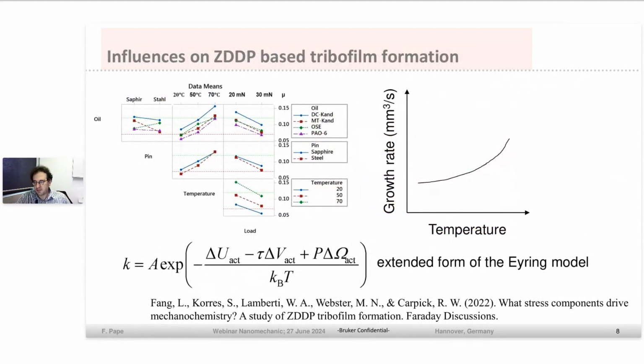What we have to know also about the tribofilm is the growth rate. We have here the form of the Eyring model, this equation, where we have in this exponent the activation energy, the delta U activation, which is like a barrier for the formation of the tribofilm. And this barrier is reduced by the shear stresses, this tau, which is acting on the volume, and also the temperature reduces this barrier.